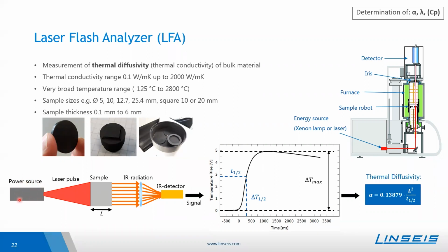The power source shoots a short, high intensity energy pulse towards the sample. The sample absorbs then the energy, and a part of it is emitted as infrared radiation on the rear surface of the sample. This radiation is collected via an infrared detector, and in the end, we will obtain a signal which looks like that, so that we can see here the temperature rise with time due to this short laser pulse put onto the sample.